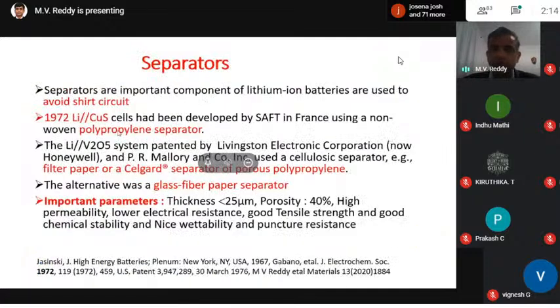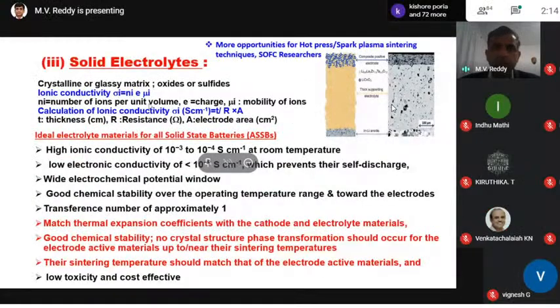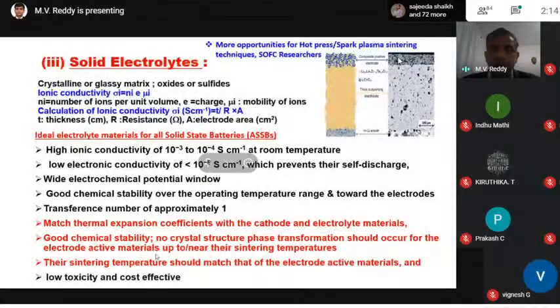Separators were already discussed. Separators are an important factor, because we must use a separator to avoid short circuit, and there is thickness, porosity, and good chemical stability, etc. Nowadays, to avoid all these flammability issues, people use all solid-state electrolytes, meaning the oxide-type materials are pressed together. Finally, we can make a cell. Again, these are very important factors. We have to look for high ionic conductivity, low electronic conductivity, and good chemical stability with respect to temperature, in the sense that the thermal expansion coefficient has to match the cathode and electrolyte materials.